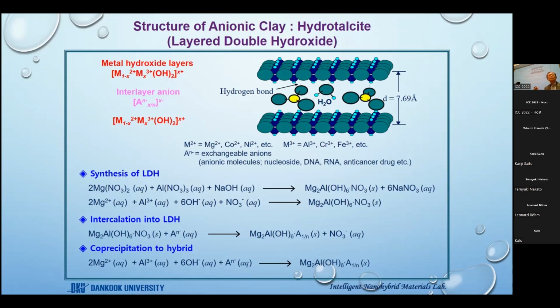But the interlayer interaction is very strong bonding. So that's why it is impossible to immobilize molecules into this two-dimensional lattice. However, if the magnesium ions are partly substituted by trivalent cations, such as iron 3+ or aluminum 3+, or other trivalent cations, then a positive layer charge can be generated. In order to compensate the positive layer charge, interlayer anions can be stabilized in between this two-dimensional lattice. In such a way, the charge compensation could occur to get a thermodynamically very stable phase.